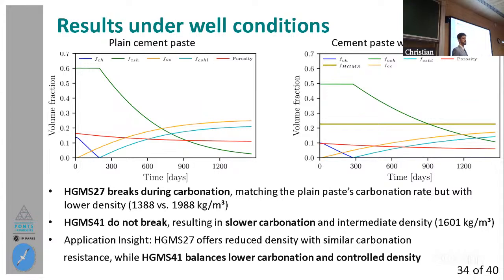which is the best of both worlds. Well, we have to mention that this could be a limitation of the model, since we are not taking into account the pozzolanic activity of this sphere, which may consume the outer shell made of glass of this hollow glass microsphere and affect, as we measured, the strength of the material, which let us break it in the carbonation cell, but here we are not able to break them with these conditions.